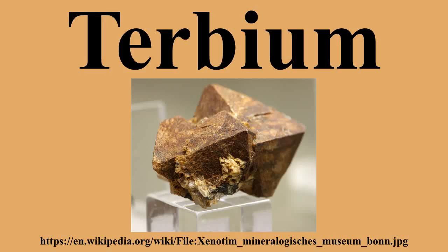Terbium(II) halogenides are obtained by annealing Tb(III) halogenides in presence of metallic Tb in tantalum containers. Terbium also forms sesquichloride Tb2Cl3, which can be further reduced to TbCl by annealing at 800 degrees Celsius. This terbium chloride forms platelets with layered graphite-like structure. Other compounds include chlorides, TbCl3, bromides, TbBr3, iodides, TbI3, fluorides, TbF3, TbF4.